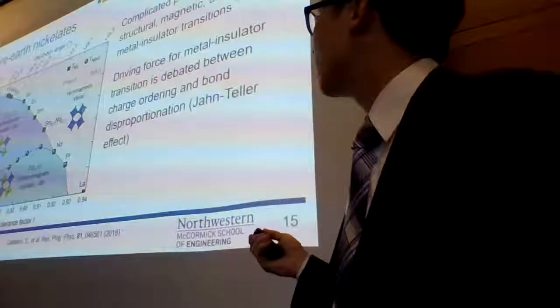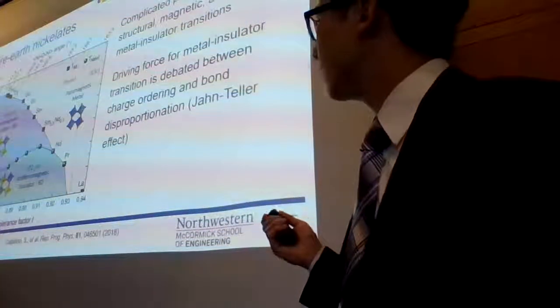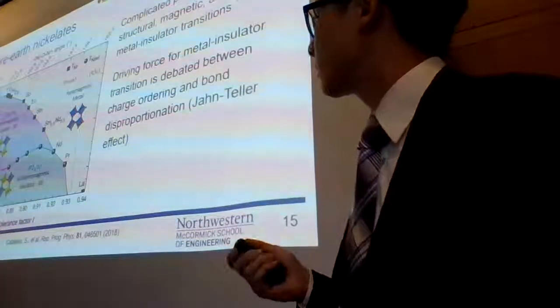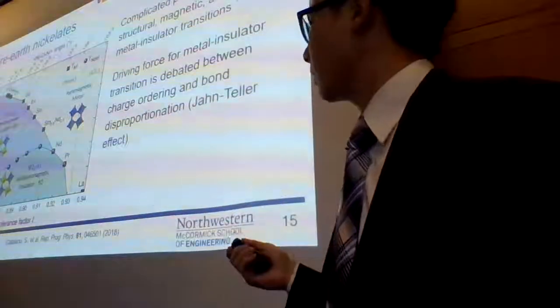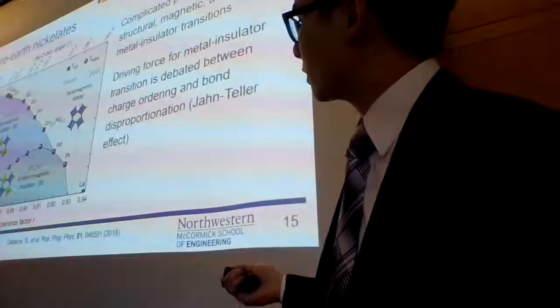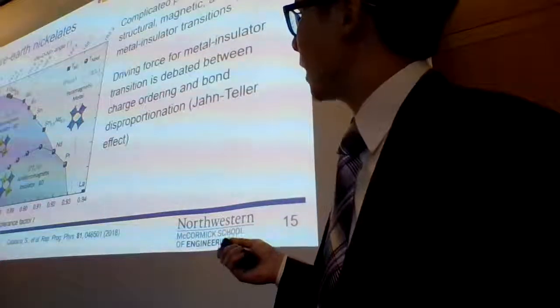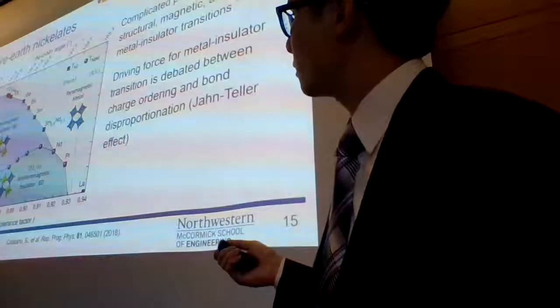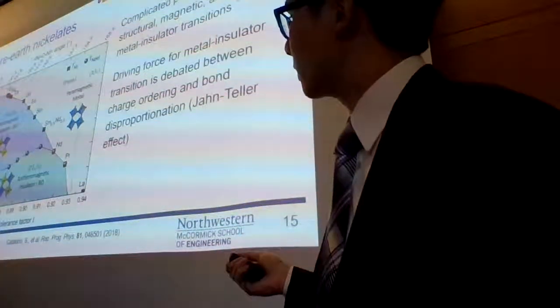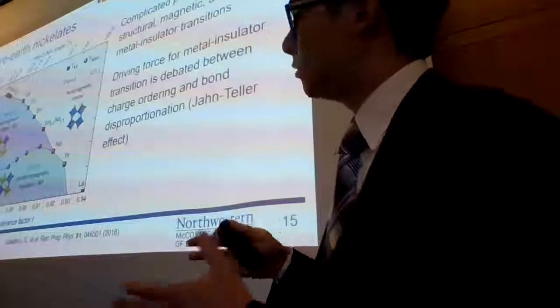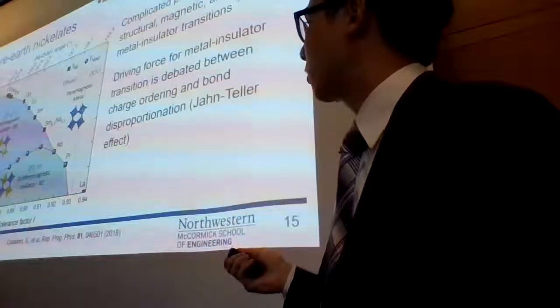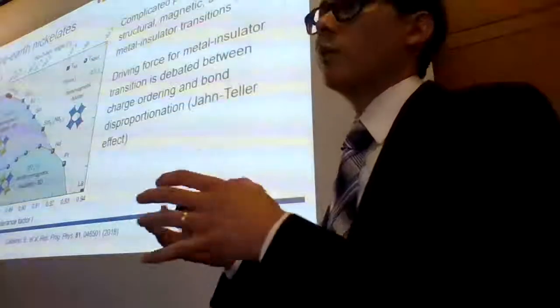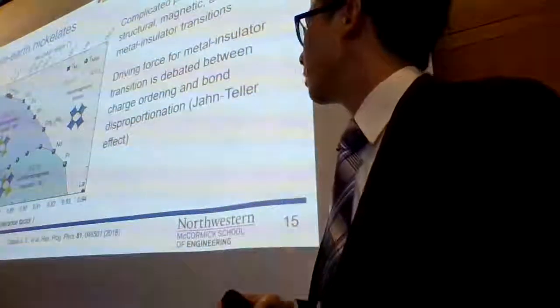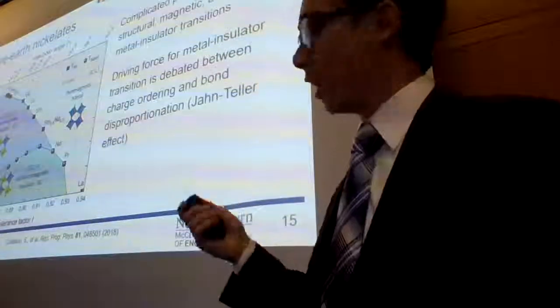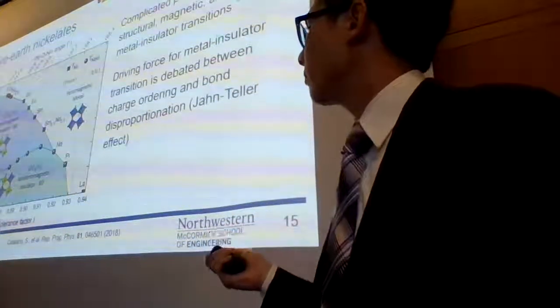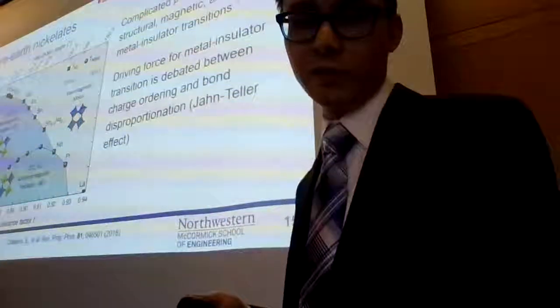under debate as to which mechanism, between charge ordering or bond disproportionation, this Jahn-Teller effect. I'll show in the next slide what those distortions actually look like. I should mention that this tolerance factor is related to the size of the rare earth cation. As you go from left to right, the size of the rare earth cation is getting larger. Essentially, due to packing arguments, as you go from left to right, the structure should become less tilted and rotated, less disordered, and more like a straight cubic perovskite. That will have important implications for the magnitude of this ordering temperature.